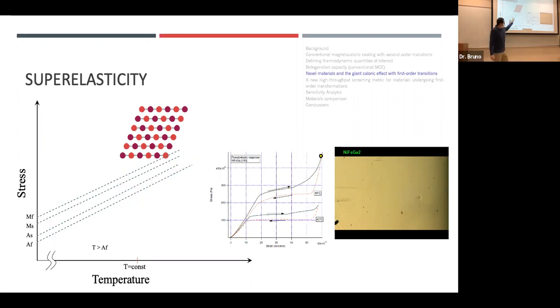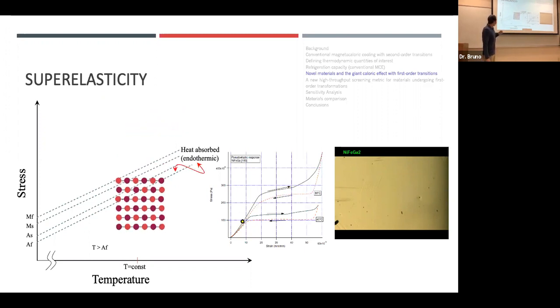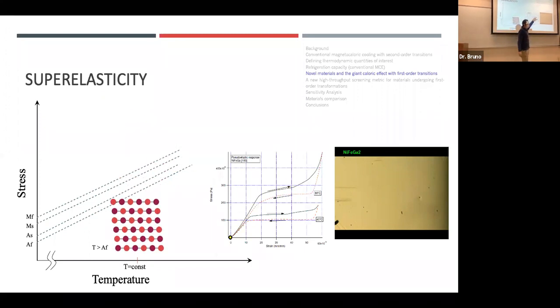So if I compress this material in austenite, it will actually heat up. Then if I release that stress, it gets cold. It's the strangest thing when you're holding it and you actually feel it get cold. And it exhibits some mechanical hysteresis because of the friction happening inside the material; there's some dissipation.